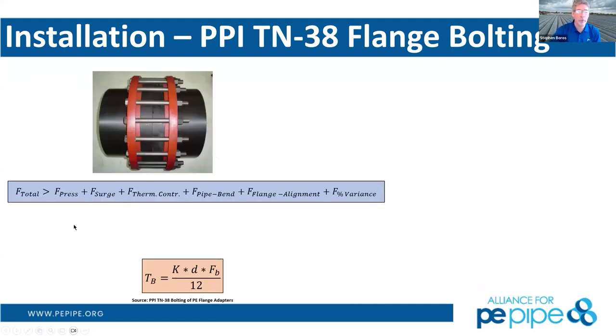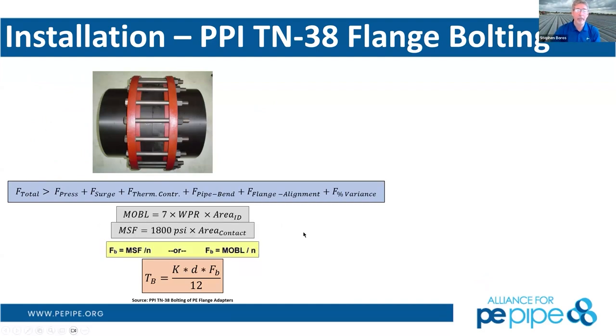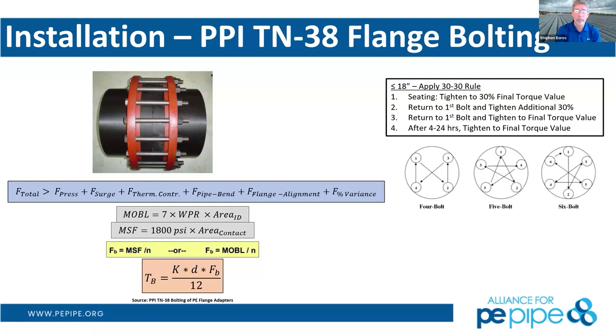So what you want the bolts to do: the bolts have to overcome the pressure, the surge, any type of thermodynamic or temperature contraction or expansion, any type of bending that might occur, flange alignment, and then whatever variance you want to take into account. The force in these bolts has to be greater than all these other forces trying to pull that apart. So once you go through that calculation, you can see that there's a certain torque value that you need to put on all these bolts to make sure that you get the right contact area and you get a fully sealed flange. Now, the nice thing about polyethylene is that with a polyethylene to polyethylene flange adapter joint, you don't even need to use a gasket as long as it's aligned properly and as long as the bolts are torqued properly.